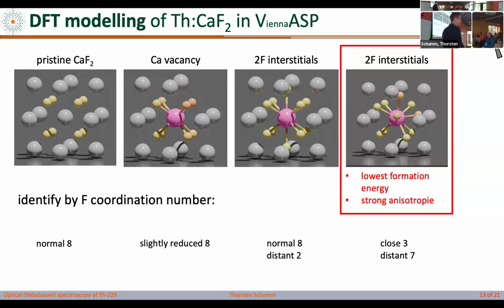Now it would be nice if we could actually experimentally determine which one it is, okay? And what would be great is if we could, on a microscopic level, look at these fluorides and see how many are there and how far are they and how are they arranged. But obviously I don't have a microscope that can zoom on these defects. And also, as I said, these thorium defects are extremely sparse. They're not the dominating species. So the material is calcium fluoride to 99.9%, and then every now and then there's this thorium sprinkle in there. So I need a method that is really very sensitive only to the defects.